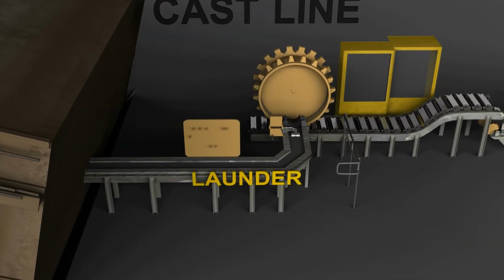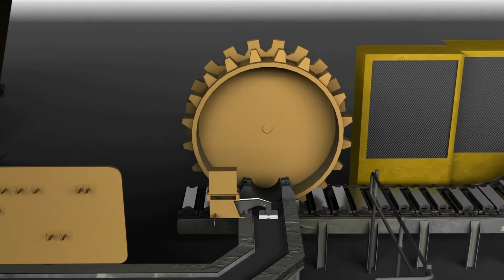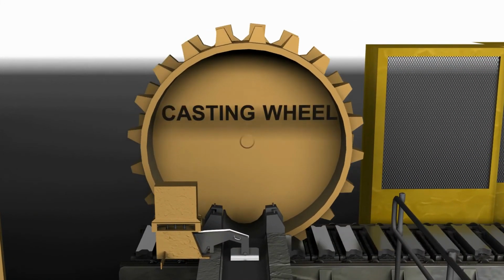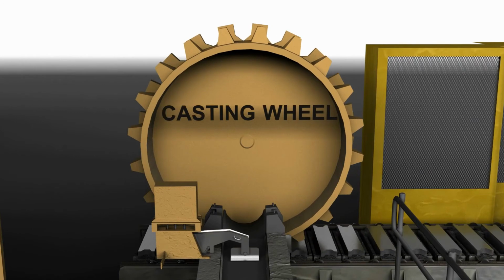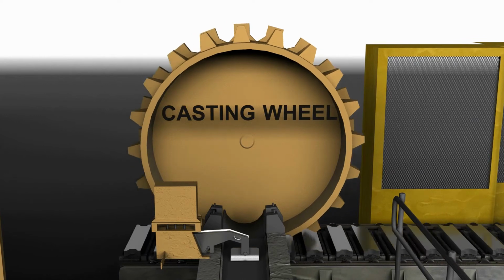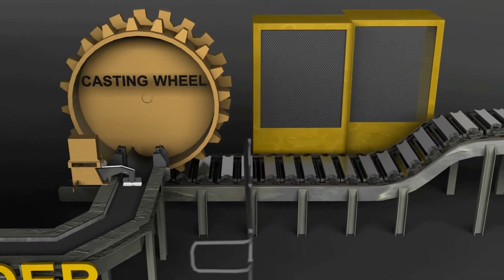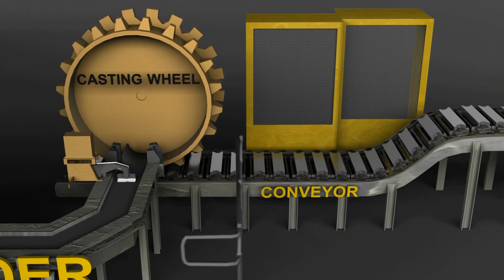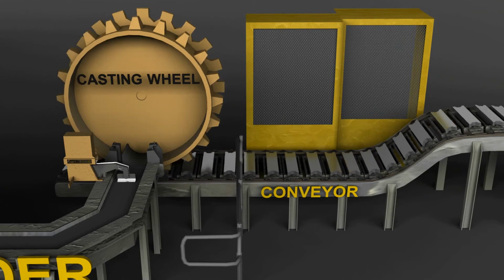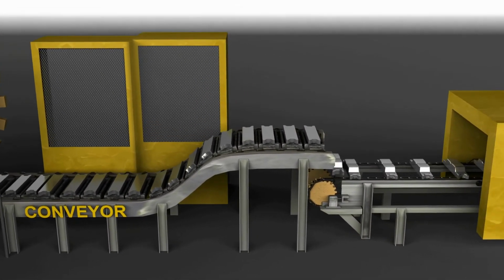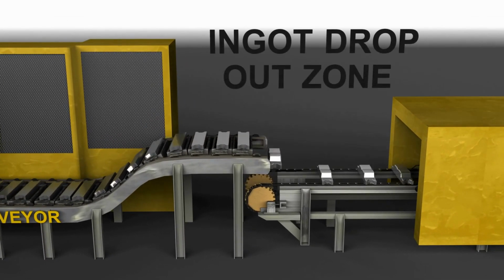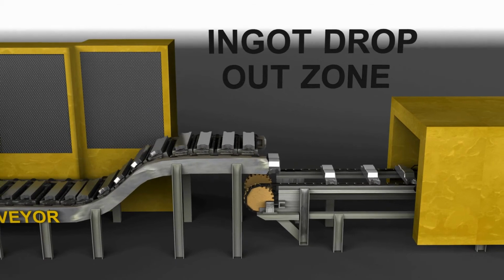The casting device is a wheel, open on one side, with a groove running around its inside circumference, which leads into a series of nozzles placed around the outside of the wheel. As the casting wheel revolves, molten aluminium runs into the groove and flows into the nozzle at the bottom of the wheel, which feeds into an ingot mold, one of an endless loop of molds, synchronized to align themselves with the descending nozzles. The ingots are skimmed before they start to solidify and are transported in their molds to the ingot dropout zone, a point at which the molds are inverted, depositing the ingots onto another conveyor.